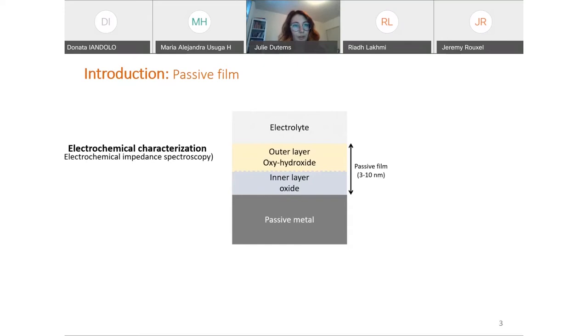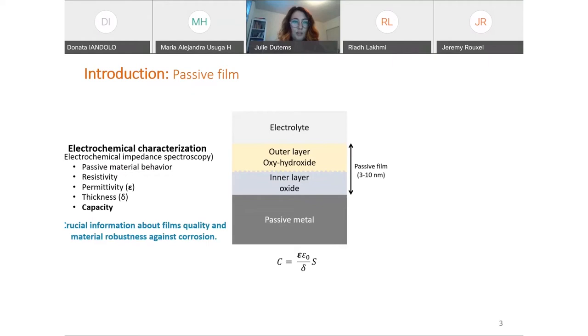You can characterize this passive film by electrochemistry and mostly by electrochemical impedance spectroscopy. It permits to give the passive material behavior, the resistivity of this passive film, and with the effective permittivity of the entire film and the thickness of the entire film, it is possible to obtain the capacity of this film. In electrochemistry, in order to characterize the electrochemical interface, the concept of capacity is very important since it is possible to model this interface by a succession of different capacities. All of that is crucial information about the film's quality and material robustness against corrosion.